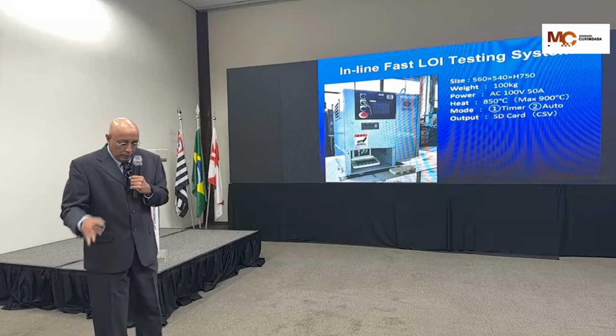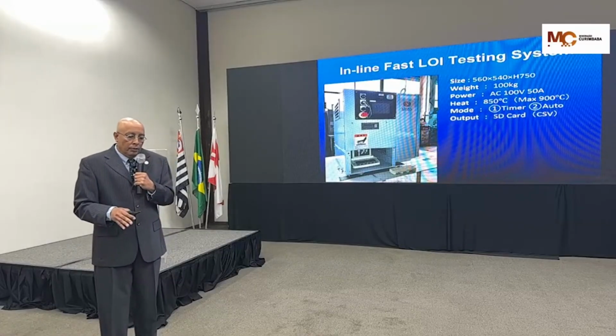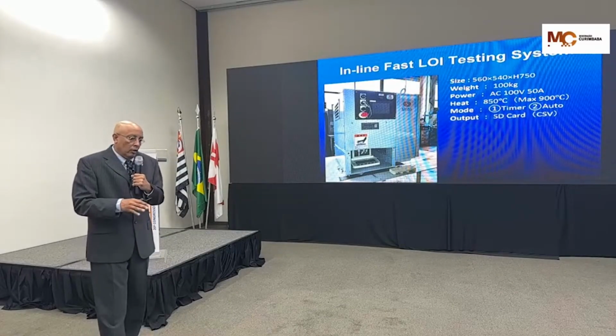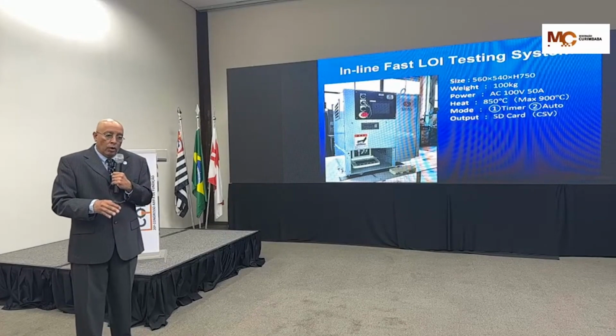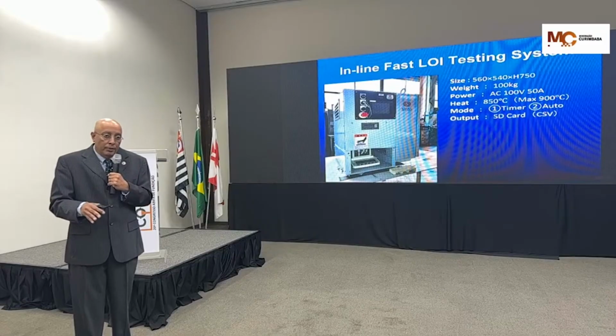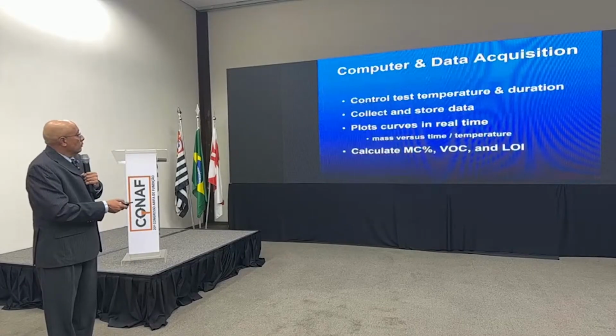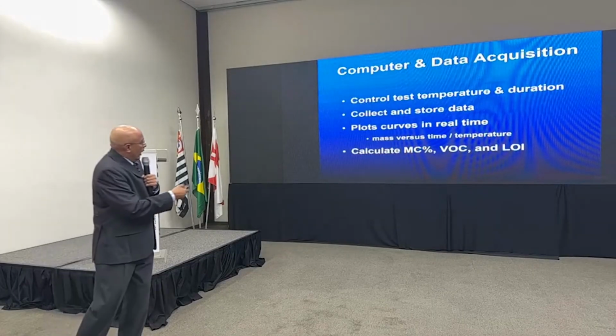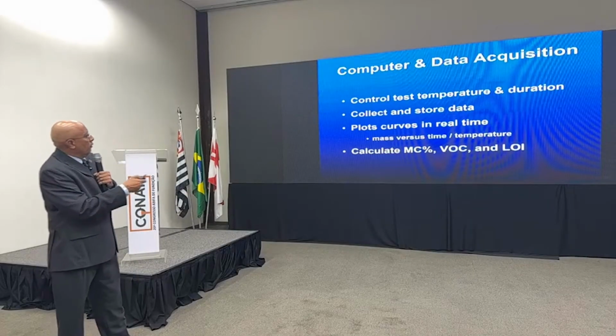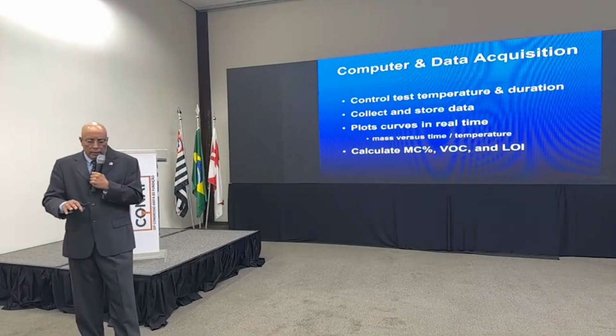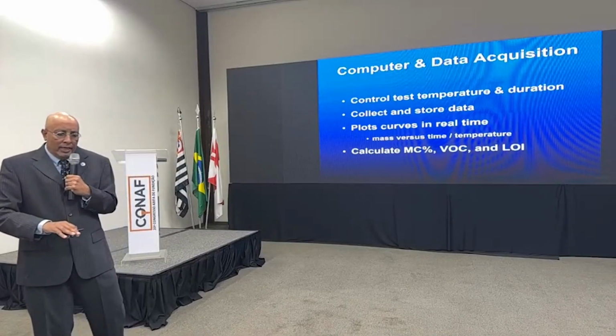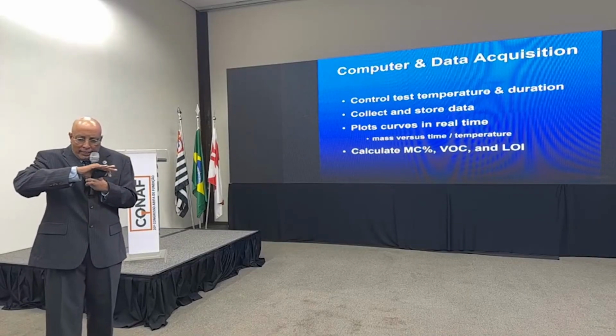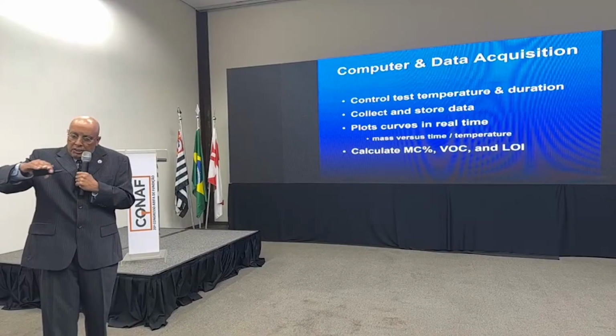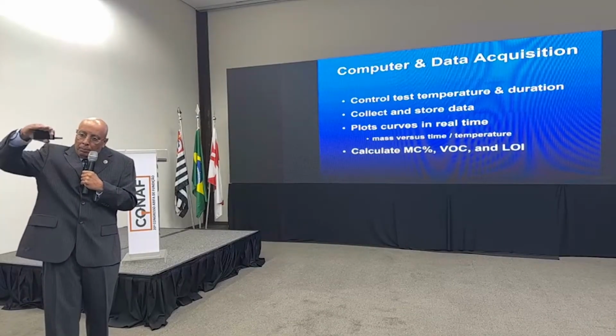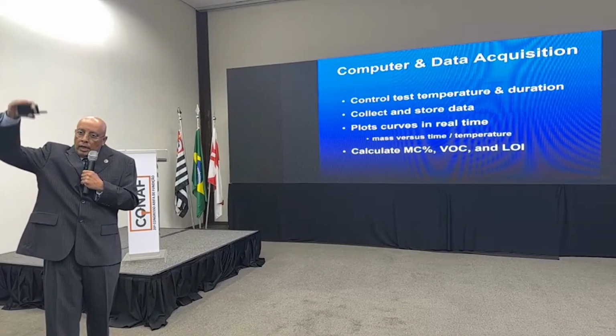In more recent times, just this year, at Western Michigan University, we have modified this technology so that we can measure the organic compounds as well as moisture all within the same time period of 5 minutes. So again, I will forego the explanation of the computer data acquisition, but what is happening, we ramp up to the AFS standard test temperature and we look for that data to flatline before we change and check the mass again to ramp up the temperature to measure the VOCs and then the LOI.